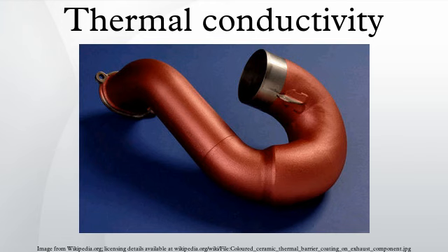Short wavelength phonons are strongly scattered by impurity atoms if an alloyed phase is present, but mid and long wavelength phonons are less affected. Mid and long wavelength phonons carry a significant fraction of heat, so to further reduce lattice thermal conductivity one has to introduce structures to scatter these phonons. This is achieved by introducing an interface scattering mechanism, which requires structures whose characteristic length is longer than that of an impurity atom. Some possible ways to realize these interfaces are nanocomposites and embedded nanoparticle structures.